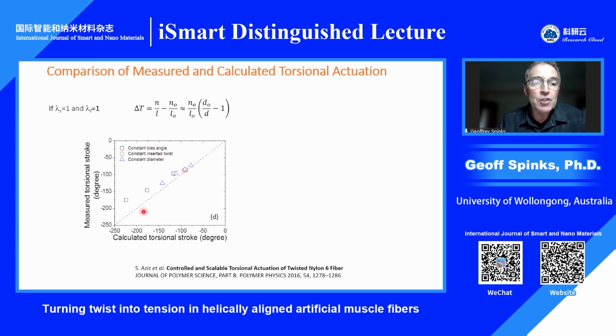And you can see in the chart that the agreement's pretty good. The symbols are the experiments and the dashed line is the expected trend. So it's pretty good. And it surprised us somewhat because we were treating these quite complicated twisted yarns as just a single helix. And obviously it's not a single helix. It's multiple helices all entangled with one another, and yet they behave much like a single helix, as shown in this example.